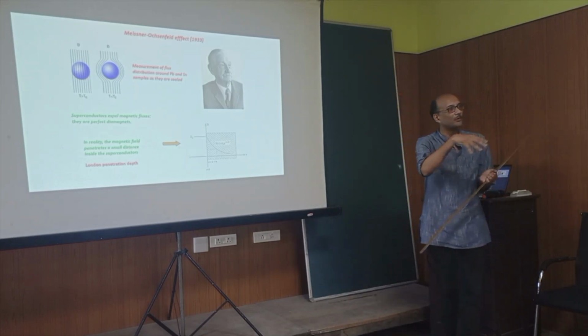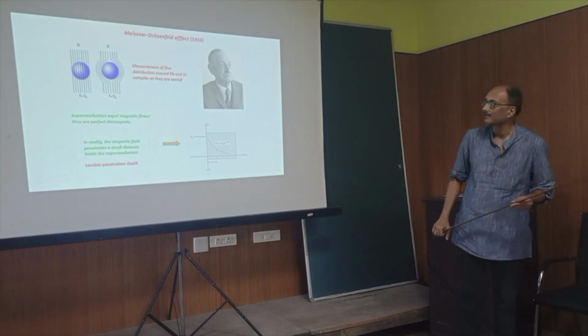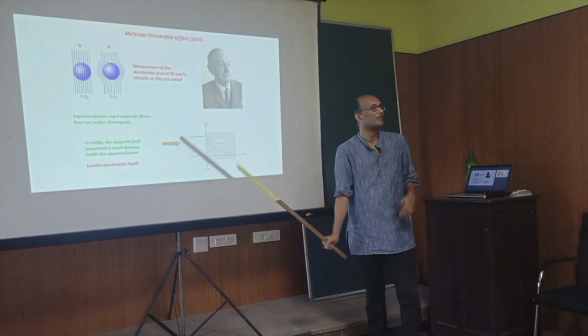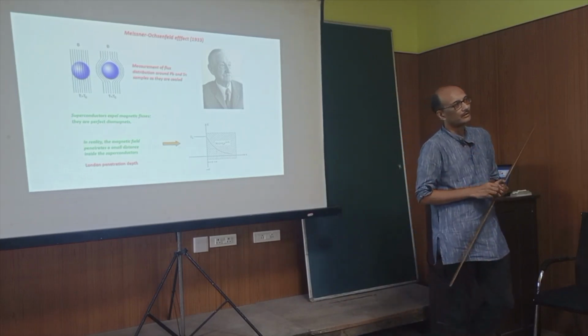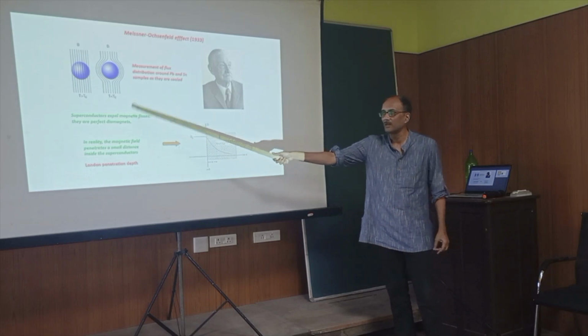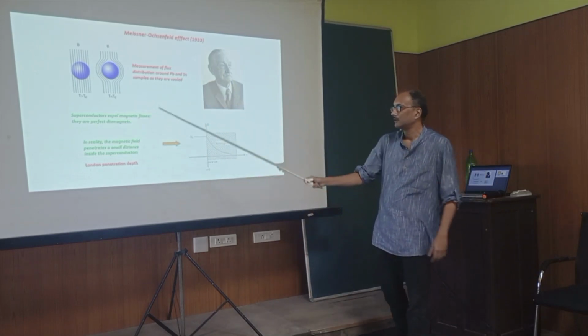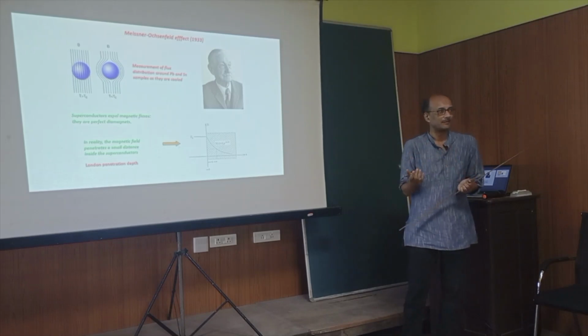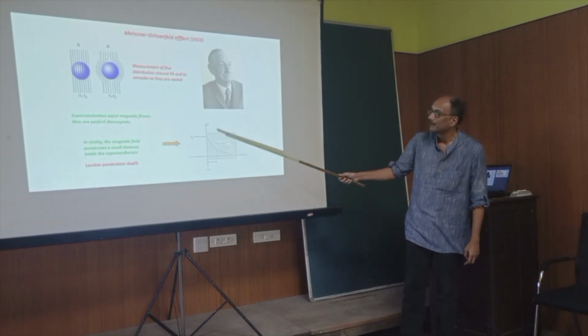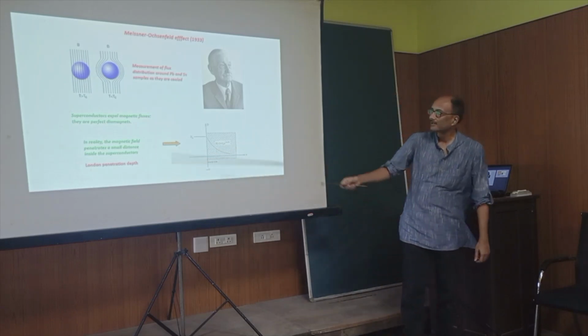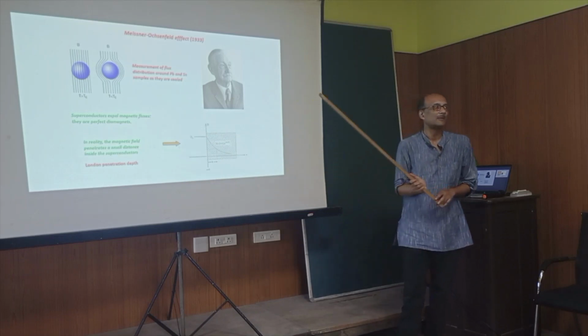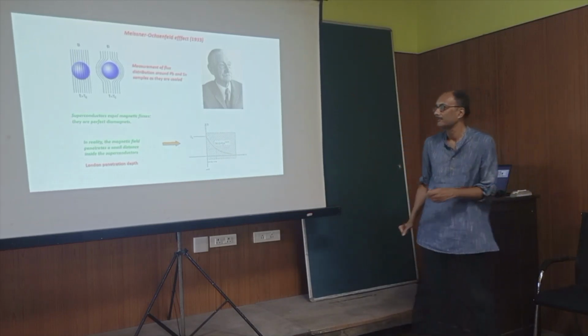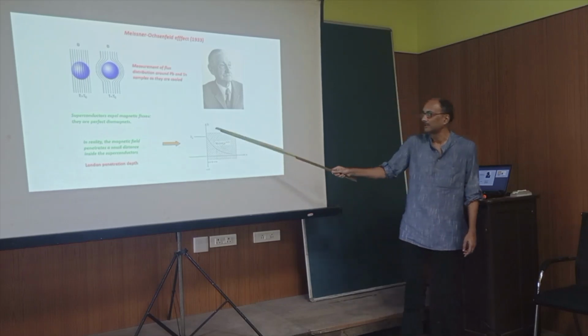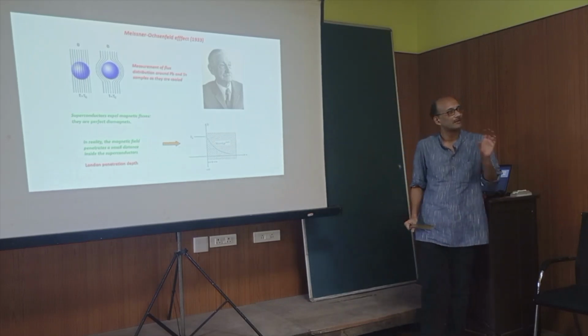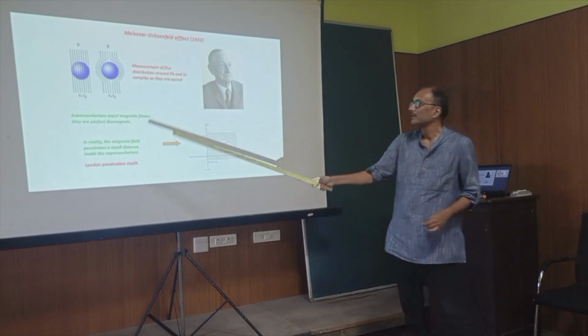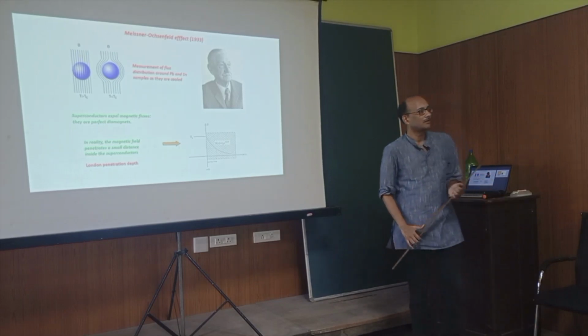So we see diamagnets, of course, among other things, like different materials and stuff like that. But here, the diamagnetic susceptibility, when you measure that, it's really, really large. So it's almost a perfect diamagnet. Okay? So, of course, in reality, the flux is not perfectly expelled. What happens is that it penetrates a little distance inside the superconductor. And there is this other gentleman called London who explained why this happens, and this is named after him. It's called the London penetration depth. It's typically the distance that the flux penetrates inside the superconductor.